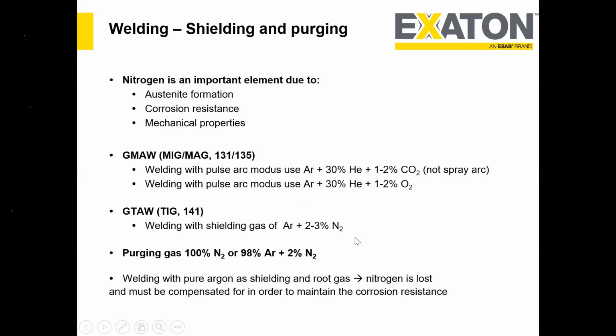So it needs to be balanced basically. Why do we need 2 to 3% nitrogen specifically in the TIG process? Because when you do TIG welding, or tungsten inert gas welding, the filler metal which has nitrogen, let's say 0.23 or 0.25 in a super duplex, this nitrogen forms nitrogen gas N2 and it evaporates. Once it evaporates, it reduces the nitrogen content in the weld metal. So we need to compensate that nitrogen amount through the shielding gas to get the desired corrosion properties and the microstructure.